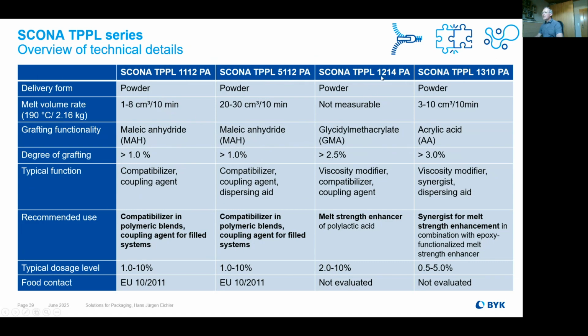Beside that, we have the 1214, which is grafted with a GMA or epoxy group. And these are quite often used as melt strength enhancer. And we have the 1310, which is the acrylic acid grafted material. And if you remember a few slides ago, I showed it as a synergist for melt strength enhancement if it is epoxy functionalized. So it's working like a booster.